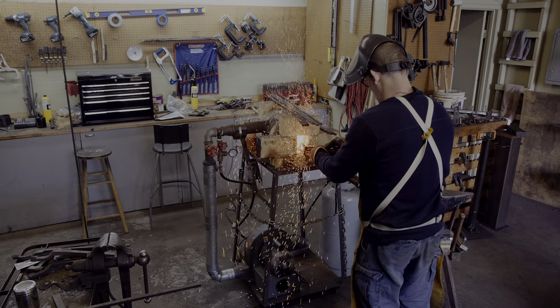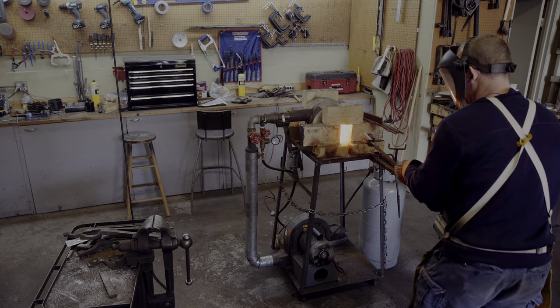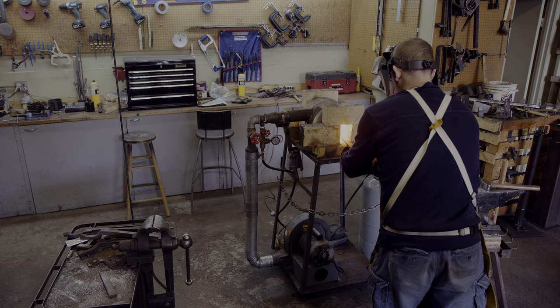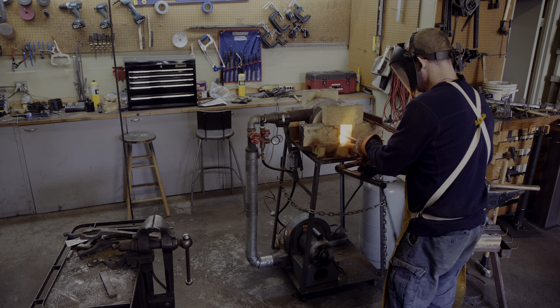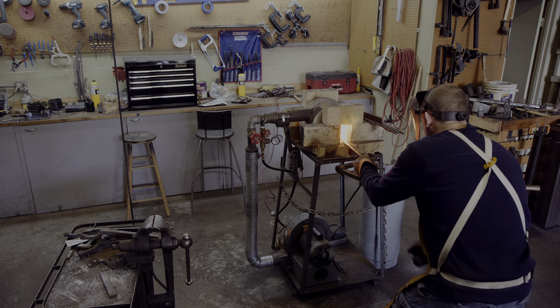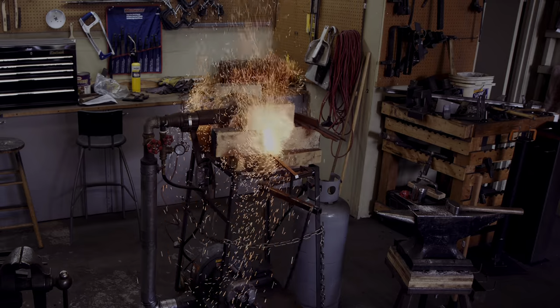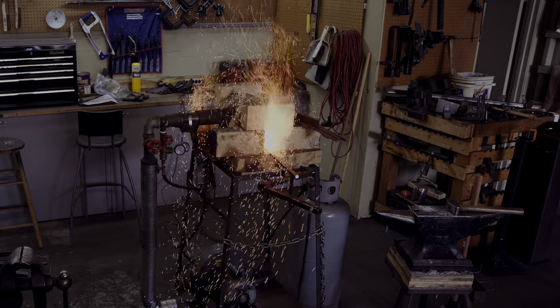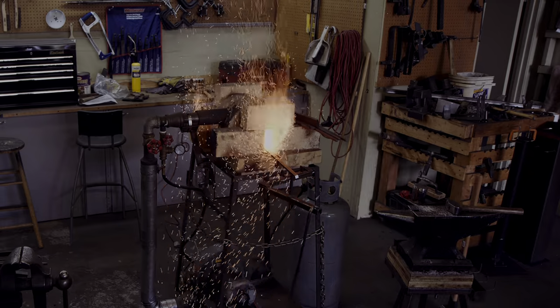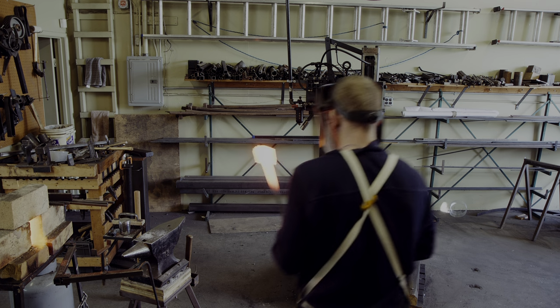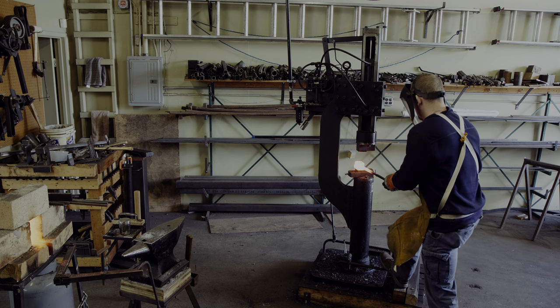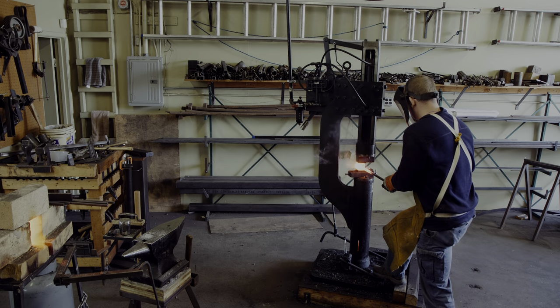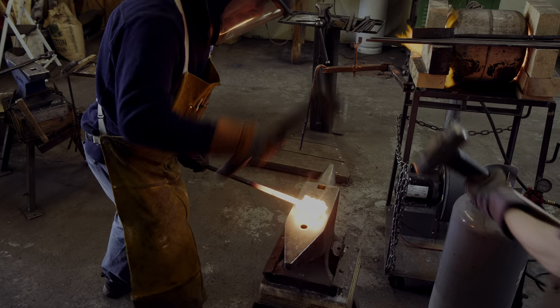Here is something you definitely do not want to repeat. I had placed a piece of charcoal into the forge to verify that the atmosphere was reducing. I went through a double check on that, as I don't want a rich atmosphere to eat the carbon in the puck. After I get it to forge welding temperatures, this is where the flux is liquid and bubbly, I am working the billet with swift hits from the power hammer. This should set the weld well.